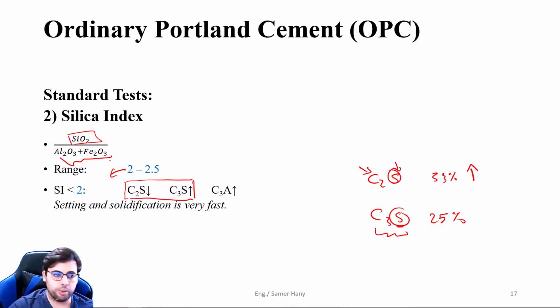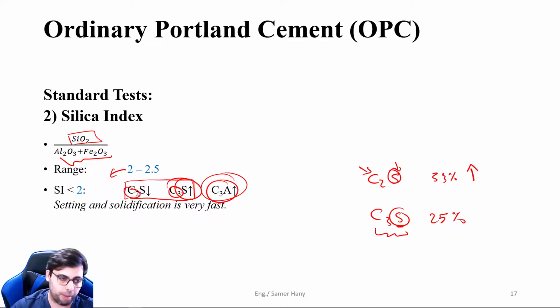When the silica goes below the standard range, that means the compound with higher silica percent will be formed in a lower extent, and the compound with the lower silica percent will be formed in a higher percent. Okay, so that's what these two actually represent. So C2S, which has higher silica content, will be formed in a lower concentration or a lower amount, and C3S, which has lower silica content, will be formed with a higher amount. And consequently, C3A will increase because we didn't consume as much calcium oxide since the silica is already down. Okay, so setting and solidification will be very fast since C3A and C3S are both up in the amounts.